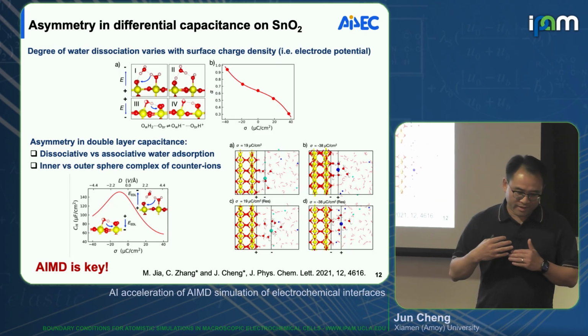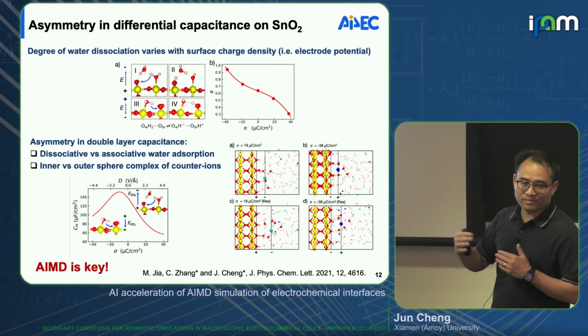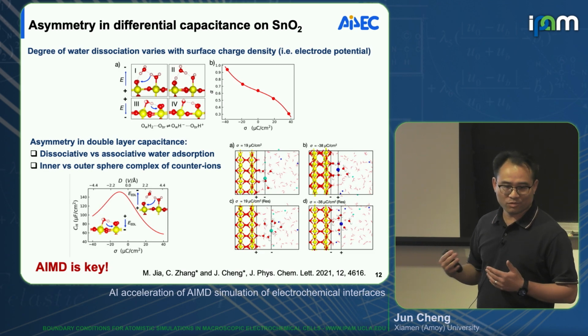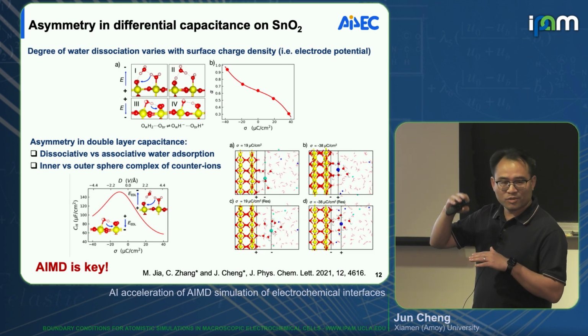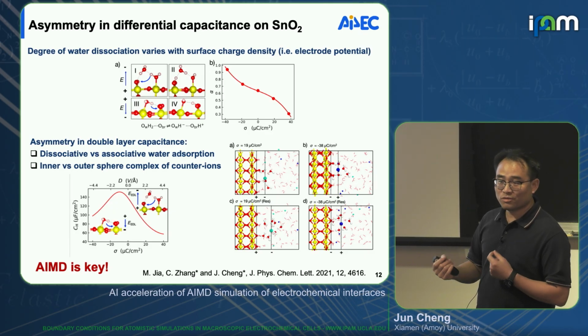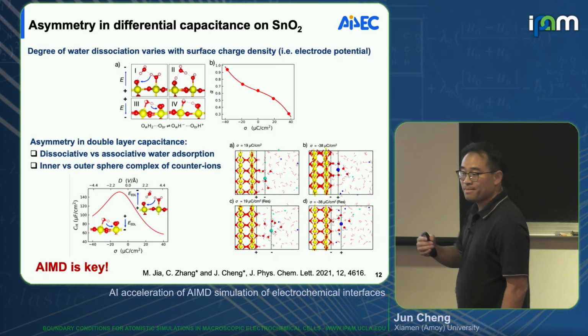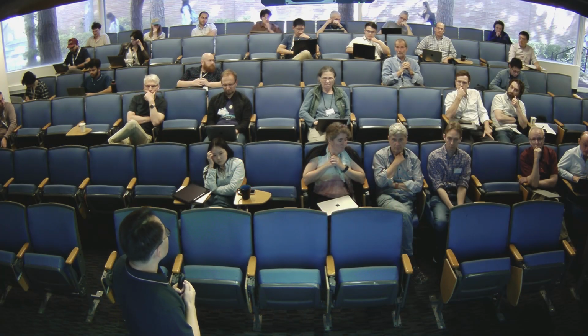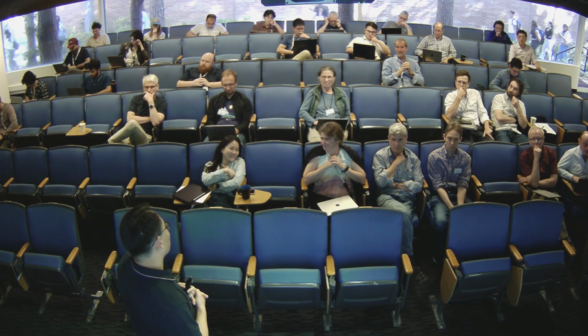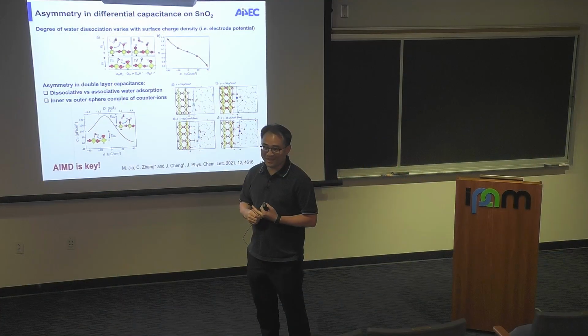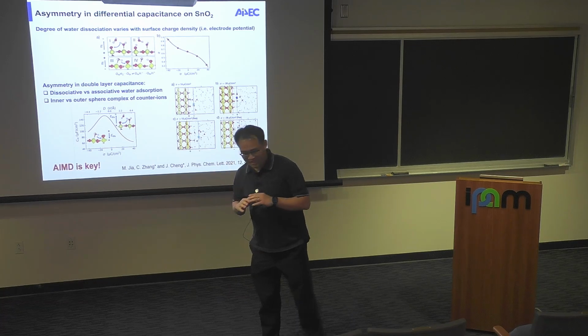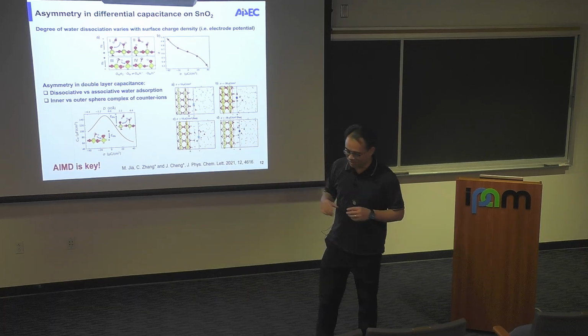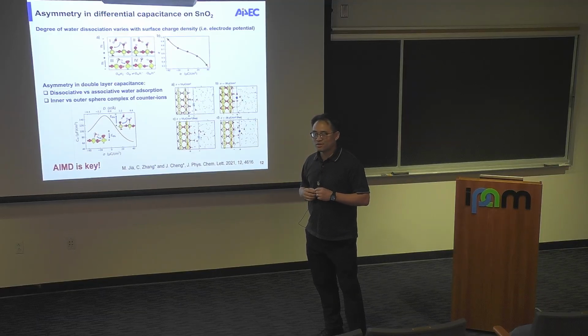They have different interface dipole. Okay, molecular water or dissociated water. So if you have a charged surface that builds up a field at the interface, it will change the water dissociation. Okay. And may I ask a question? How do you define the surface charge density in your calculations? Yeah. Again, we do a really simple trick, right? We just add a certain number of protons on the surface and put in the counter ion. So we do a fixed number of particles. It's not like a grand canonical thing, right? Particularly when you talk about pH, that's basically constant chemical potential for the proton.